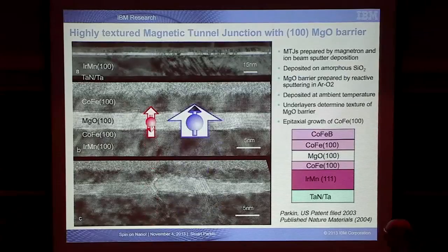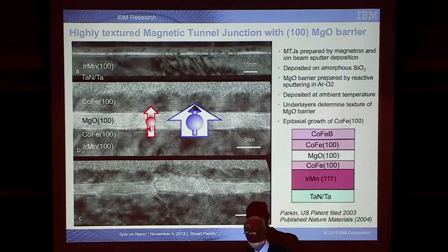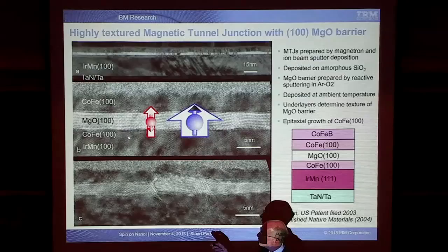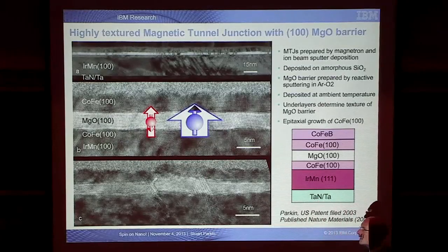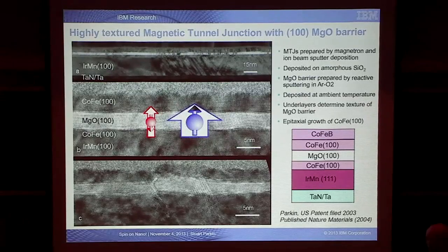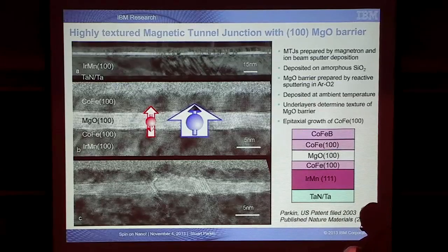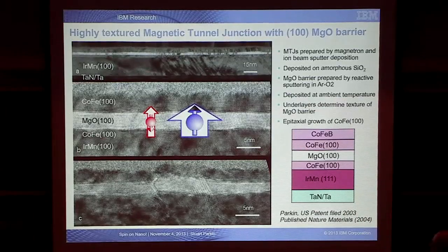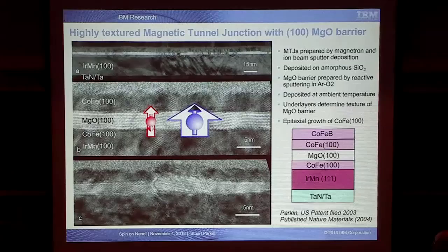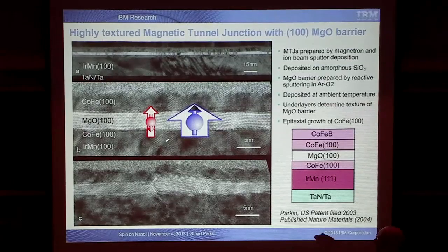is important. And it turns out if we use special magnetic materials, in particular cobalt iron alloy, which has a certain type of crystal structure, then it turns out that the electrons of this spin orientation, this blue spin orientation, their wave function is very delocalized. So the probability of tunneling is much higher across this insulating material than the red electrons, which are much more localized. So their wave function barely makes it at all across this insulating material.